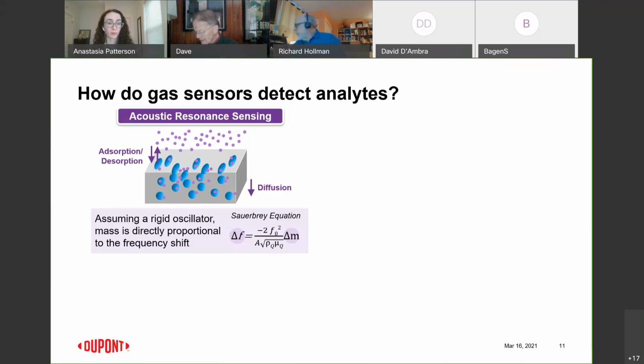And assuming that our substrate is a rigid oscillator, which is a good assumption for these devices, the mass difference as the gas absorbs and sticks to the substrate is going to correlate directly to the difference in the frequency of the oscillation of the substrate. So that's the signal we're getting. We're basically counting up the mass of the gas that interacts with the substrate, and the signal we're getting out is due to a frequency change in the oscillation.